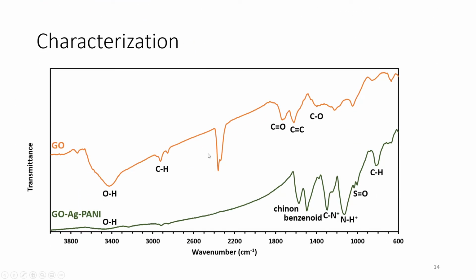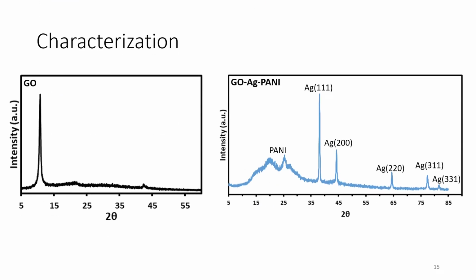The FTIR results of graphene oxide and graphene oxide silver polyaniline nanocomposite show the typical FTIR spectra of these materials, and X-ray diffraction pattern of graphene oxide shows the typical sharp peak at around 10, and our ternary nanocomposite reveals a broad band corresponding to polyaniline and also a crystalline peak at around 25 degrees. Also, it's shown that silver nanoparticles are formed, and all of silver's typical diffraction patterns are seen in this figure.